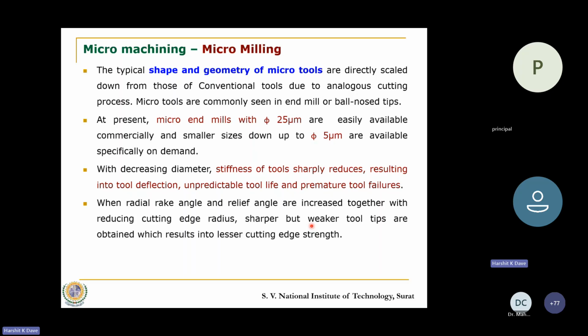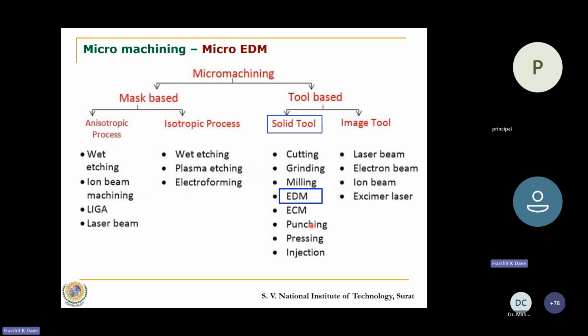So when you reduce the diameter, the stiffness of the tool will reduce. It will become soft. It will result in deflection. In most cases, we have tried with 300 micron and 200 micron end mill cutters, and during the first or second cut itself, we have seen that often the tool breaks. So premature tool breakage or tool failures occur when we are working in this domain. So having the tool and carrying out the process is the next level of problem. But the first level of problem is making these end mill cutters and then using them for our application. Now that is something about micro milling.